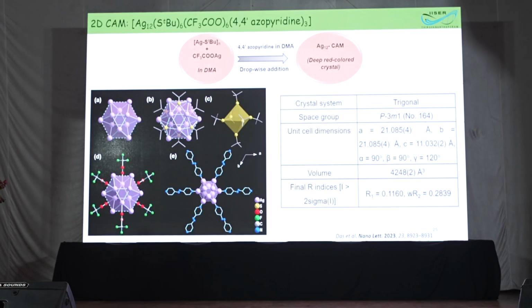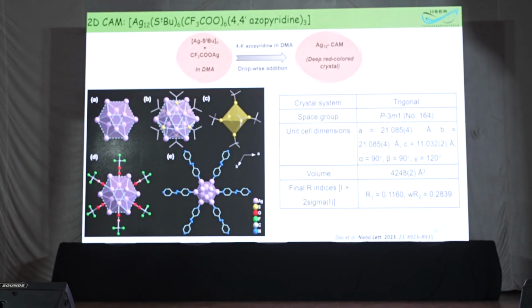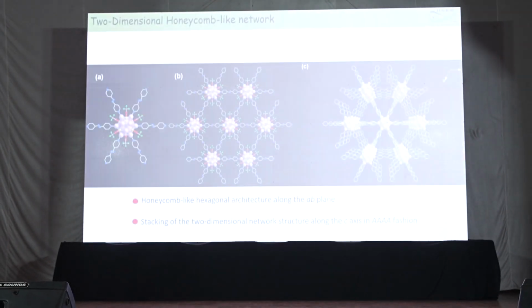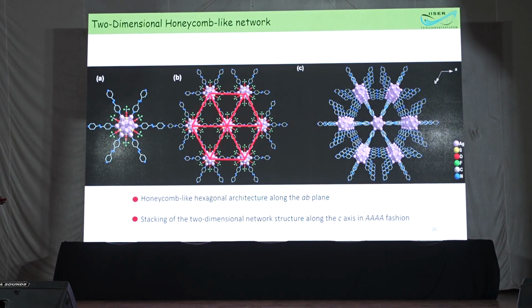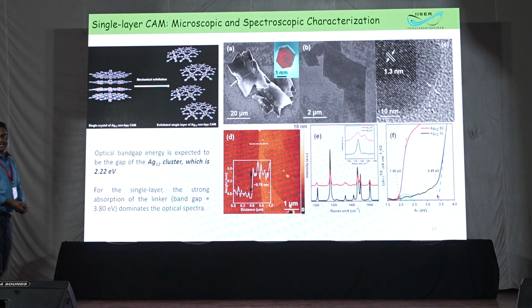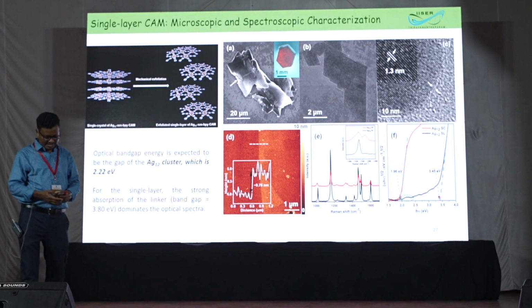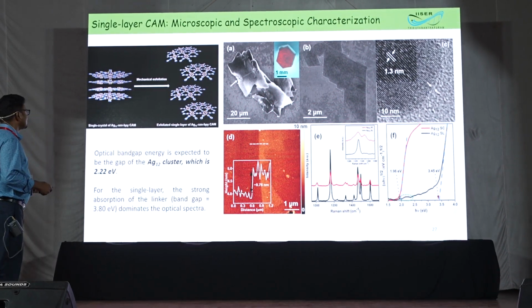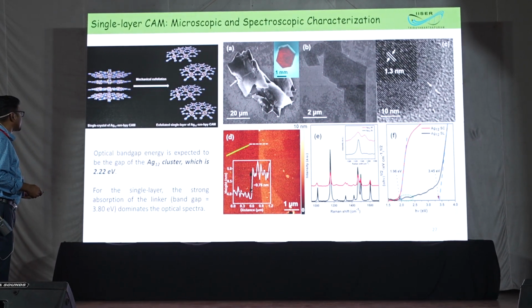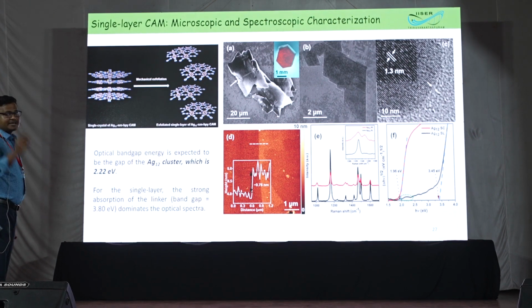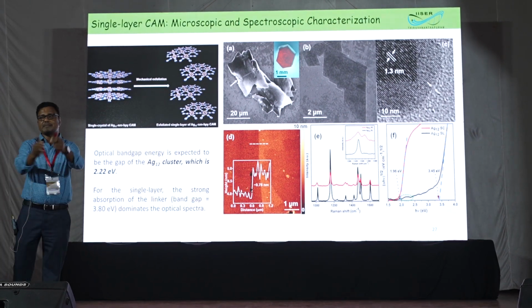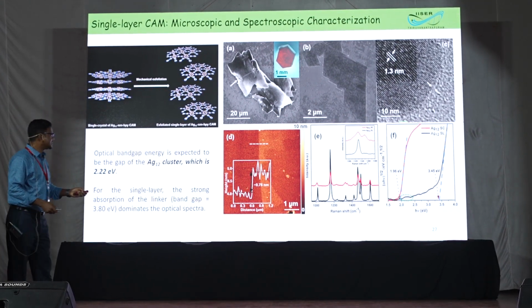So we have synthesized the Ag12 cluster, which is linked by azopyridine, and this is the structure analysis. We can see that this is a beautiful honeycomb structure, stacked in AA fashion. So we did mechanical exfoliation and got the single layer, which we characterized by different techniques like AFM and TEM.